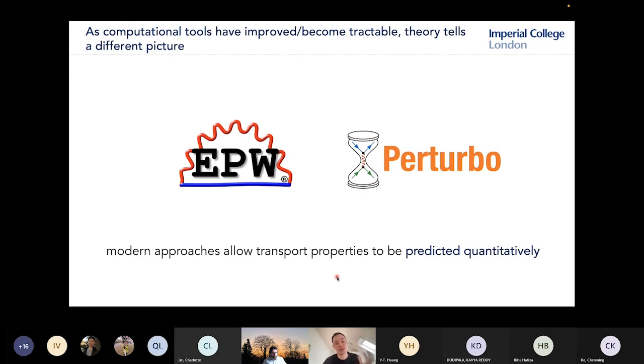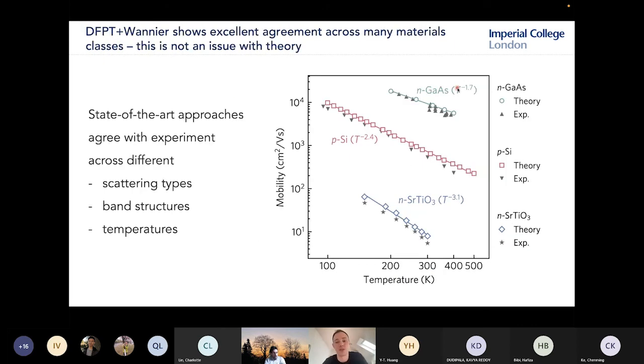for calculating transport quantitatively. I mentioned DFPT before. That's mainly implemented in these two packages, EPW and Perturbo. Just to show you how accurate these approaches are, this is some results on 3 semiconductors: gallium arsenide, silicon, and strontium titanate. These are 3 very different materials with different band structures and different scattering physics, and the DFPT approaches really agree both on magnitude and the temperature dependence as well.